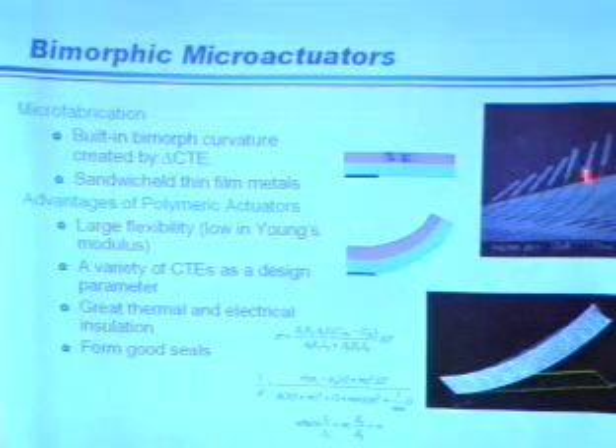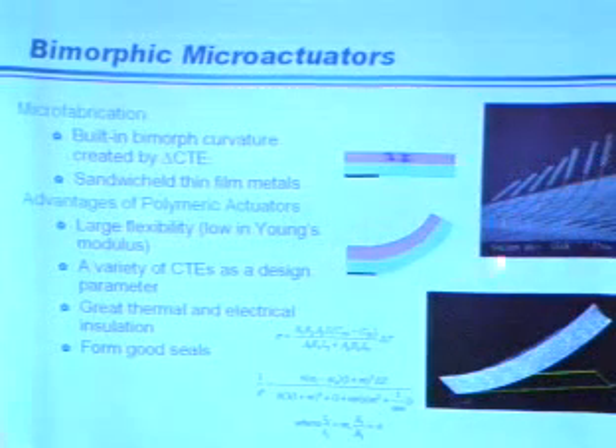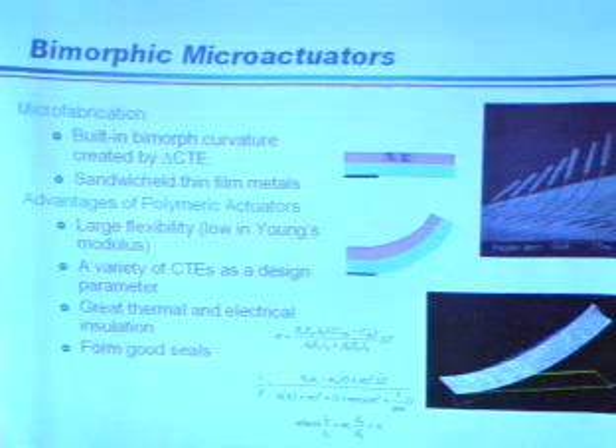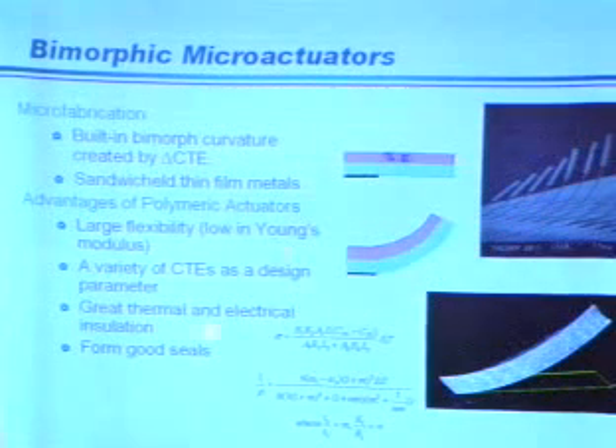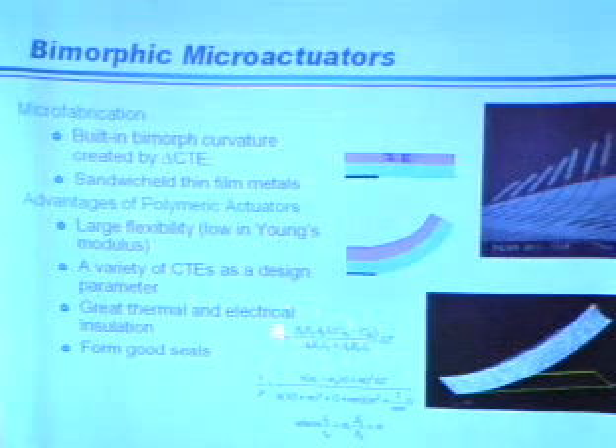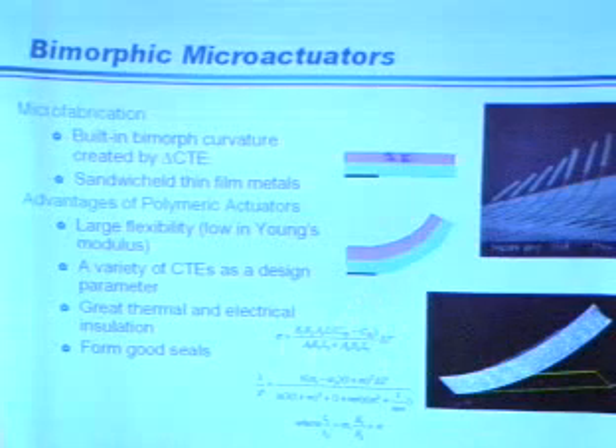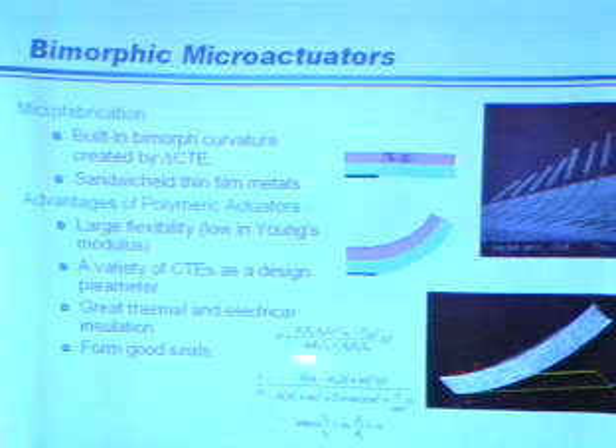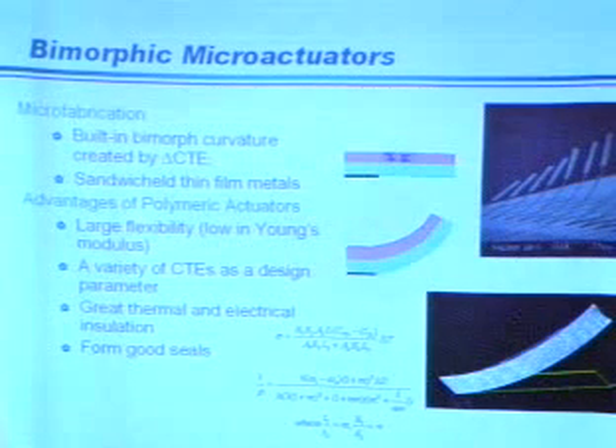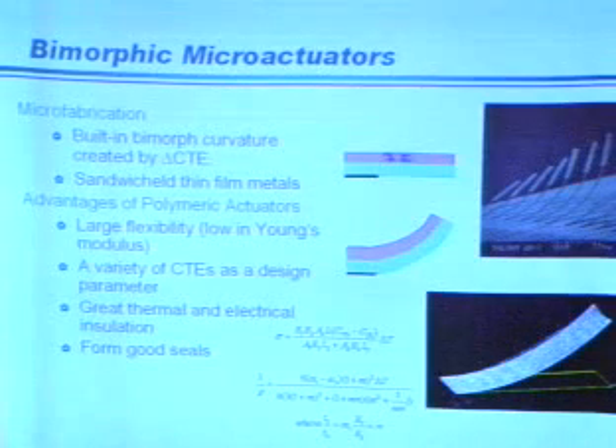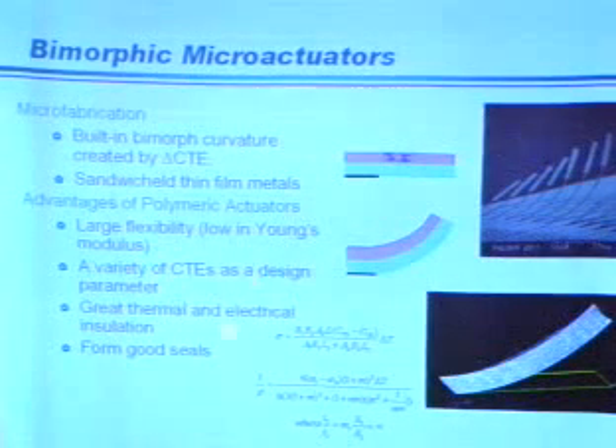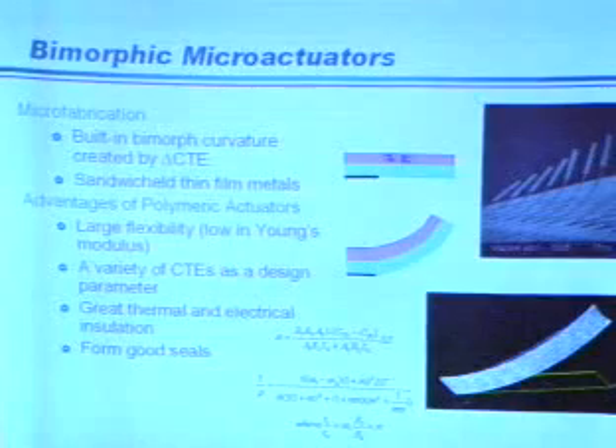And this is just some work we did earlier, just using different lengths, which allows you to have different initial curvatures. If you're using polymers, even more so, you can get the stress. Here's a stress relationship between the difference in CTE as well as the difference in temperature. You can calculate the radius of curvature with Timoshenko's formula. Again, back to the polymers: you can get the insulation you need for most fluidics applications, good seals, and good insulation, so you can embed electrical components that are shielded from each other.